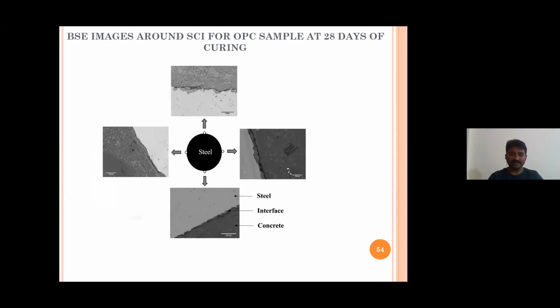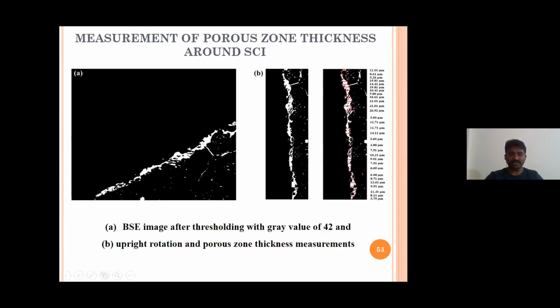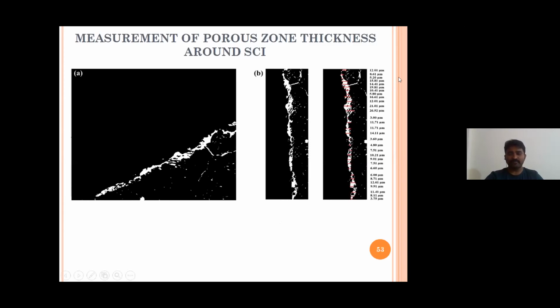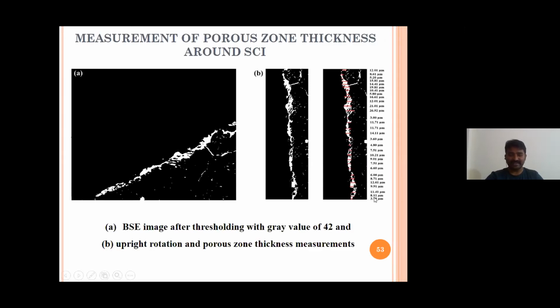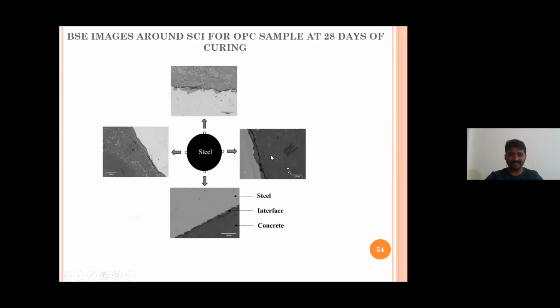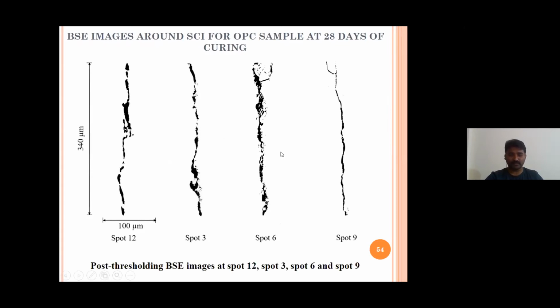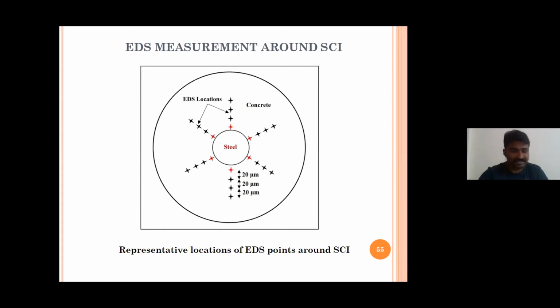There has to be some statistical value to prove that 12 is the best number of selections. For that we have used the Student's t-distribution factor. From that, if you measure at 12 locations, and at each location you measure at least 22 values, we have measured more than 22, 30 plus. In that case, we can prove that the values that we are measuring are statistically correct. Okay, so these are the porous zone thicknesses at those four locations. That is how we measure the porous zone thickness.